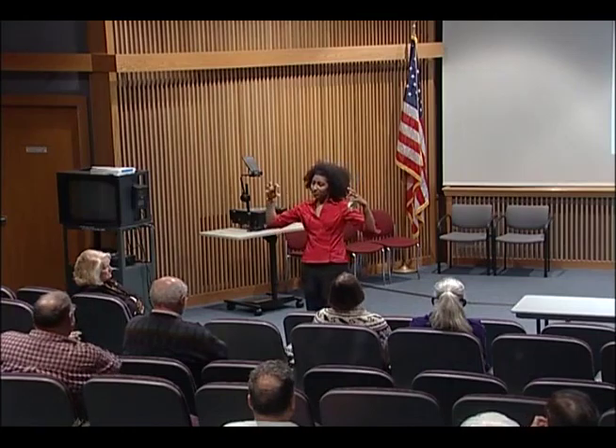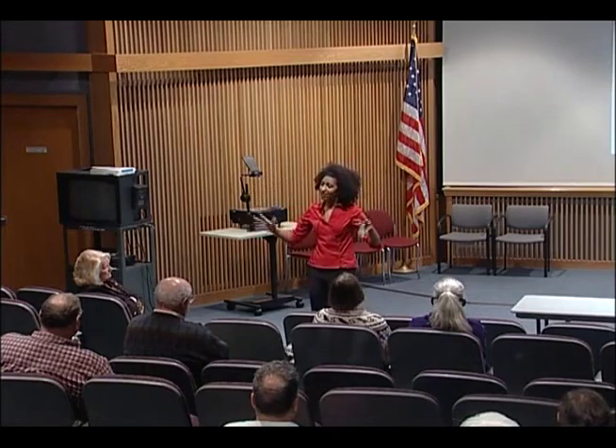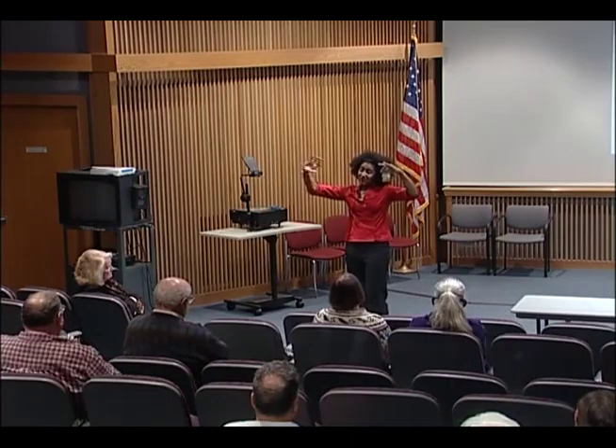I didn't tell you, we also did another model, which is of just the jawbone on its own, and loading it to see how the jawbone as a whole responds. This is another numerical model just based on the jawbone. And that one has given us some really interesting outputs in terms of telling us how much that stress penetrates into the bone, so not just at the surface, but also how much it penetrates into the bone. And we're finding the load that it takes to break the jawbone on its own without the whole whale being involved. So that's a pretty cool project too. And we've also validated that. We've taken and strung up that whole 14-foot bone and then hung weights from it, attached strain gauges to it to see just how that bone's responding. So we do have some real life validation of our modeling exercises.